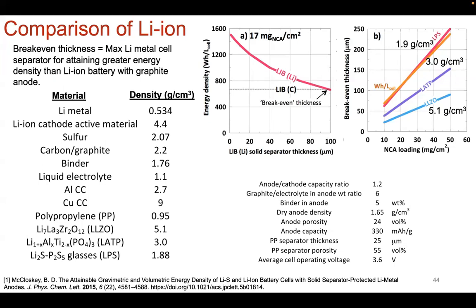Okay. And in terms of the choice of the separator, it depends. If you choose lithium polysulfide versus LATP versus LLZO, they have different densities, and thus the different thicknesses will also have different mass, which will then affect your overall capacity. What you see here is, depending on the NCA loading, you're going to need different thicknesses and different amounts of protection, because you're going to have different amounts of lithium that you need to protect. So the break-even thicknesses will change as a function of your mass loading for your cathode as well.